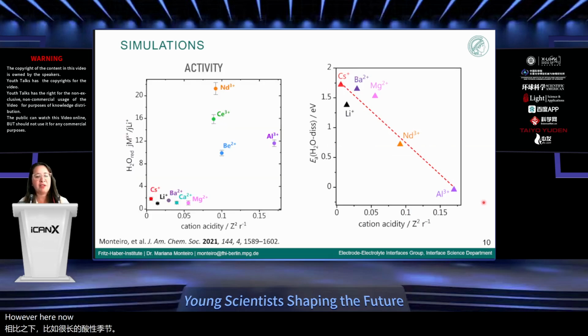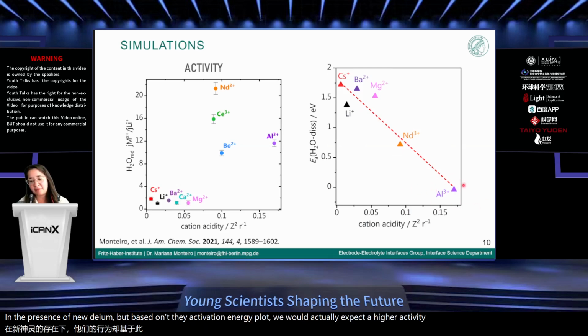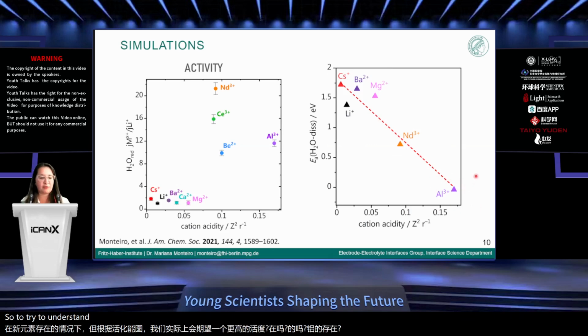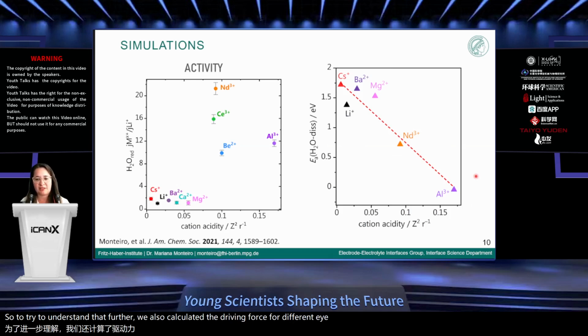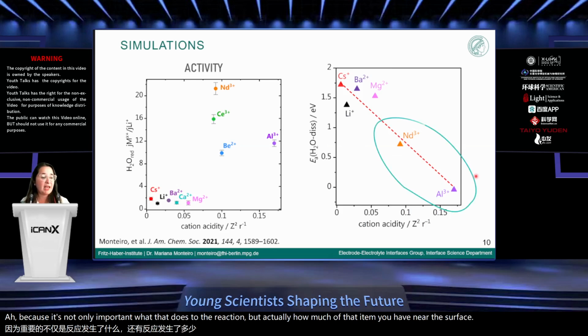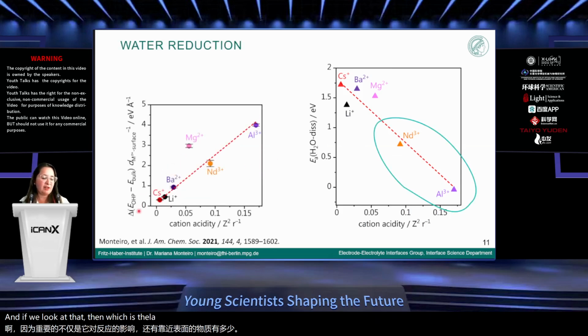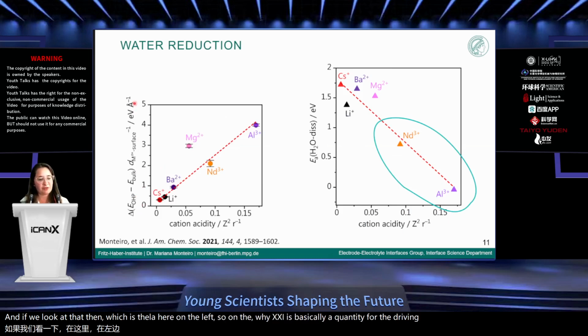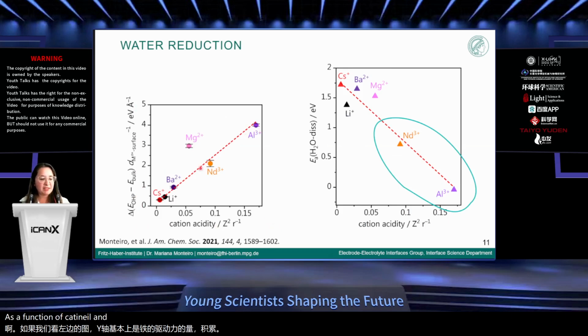However, if we look at our activity, the activity is actually higher in the presence of neodymium, but based on the activation energy plot, we would expect a higher activity in the presence of aluminium. So to try to understand that further, we also calculated the driving force for different ions to accumulate at the surface. Because it's not only important what the ion does to the reaction, but how much of that ion you have near the surface. If we look at the plot here on the left, the y-axis is basically a quantity for the driving force of ions to accumulate as a function of cation acidity. And we see that the non-acidic cations are at much larger quantities at the interface than their acidic counterparts. So that helps us to understand why neodymium is the best performing ion for water reduction.